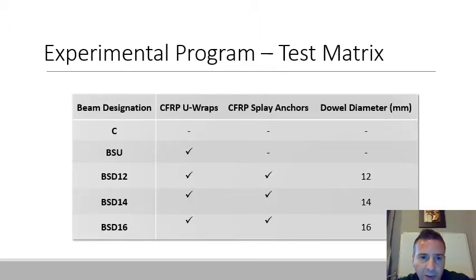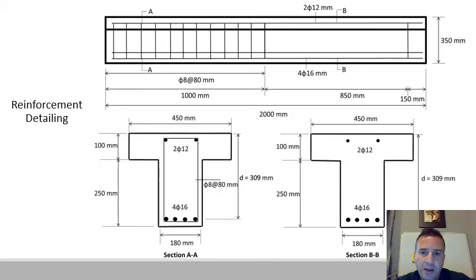So we use epoxy to anchor the sheets. We have in total for this presentation 5 beams: a control, a strengthened specimen with U-Wraps but without anchors, one with anchorage of 12 millimeter diameter splay anchors, one with 14, and one with 16. Here are the variables. And this is the control specimen.